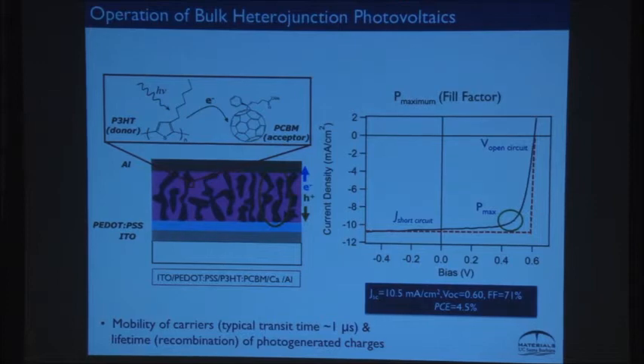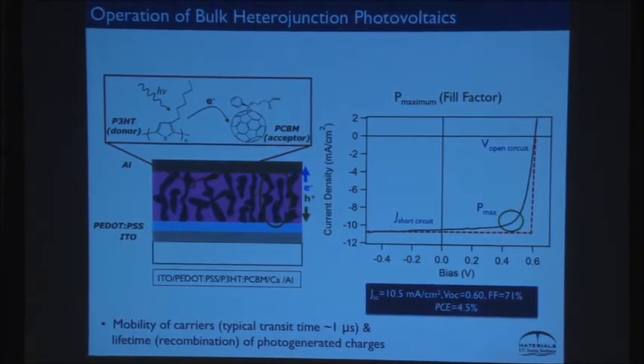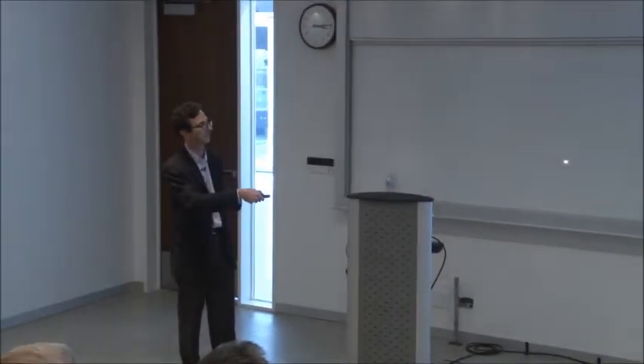Now, the other thing that matters for power conversion efficiency is basically where the maximum power point is. You'd operate a solar cell where you can extract the most power from the device. And that's here. That's how I just multiplied J times V to get that number. And we use a metric called the fill factor to keep track of that. And the fill factor is defined if I take the short circuit current. Should be actually right on top of that.